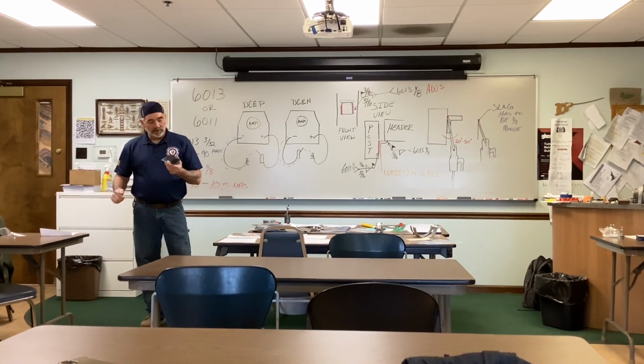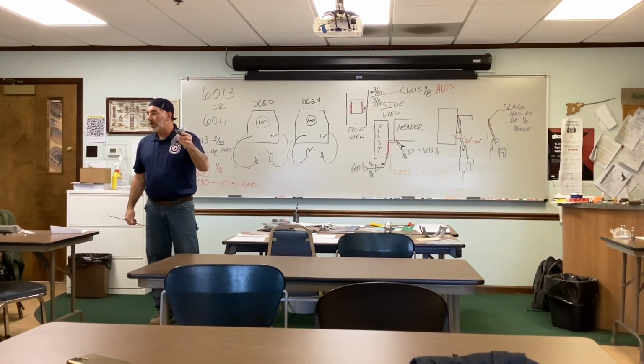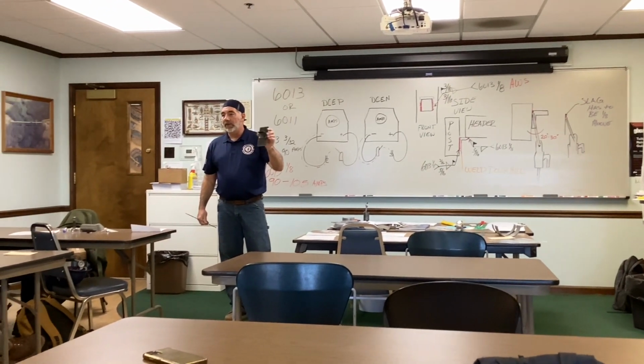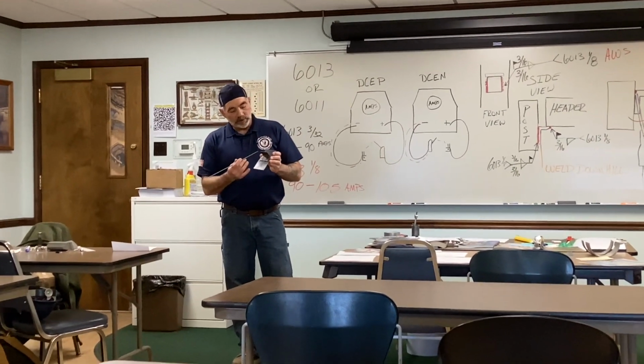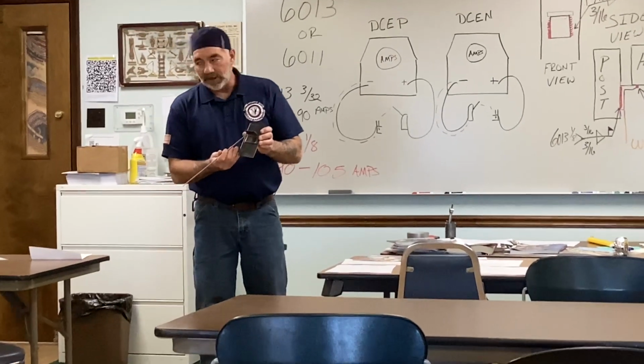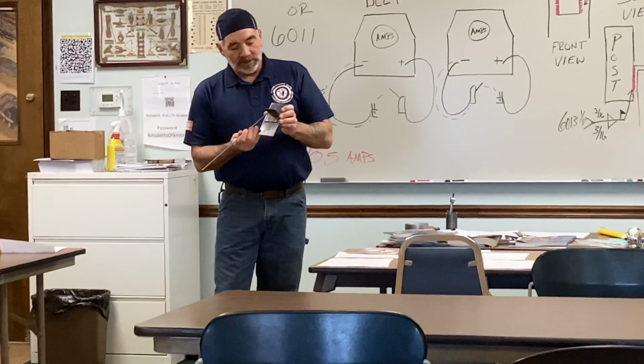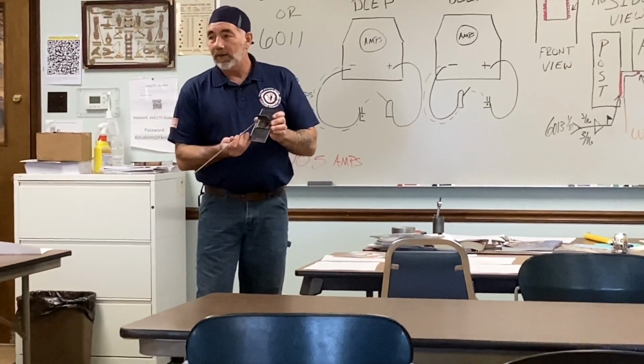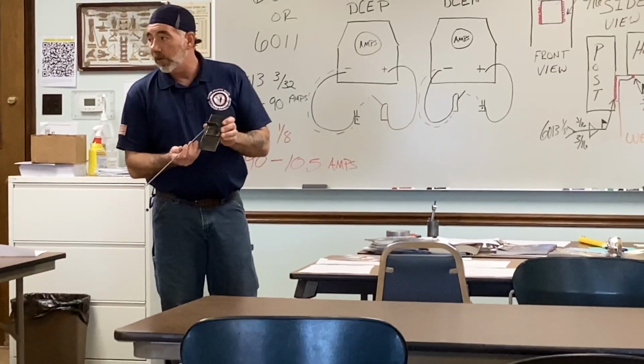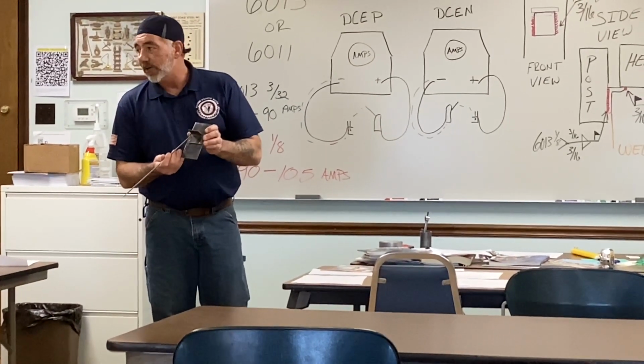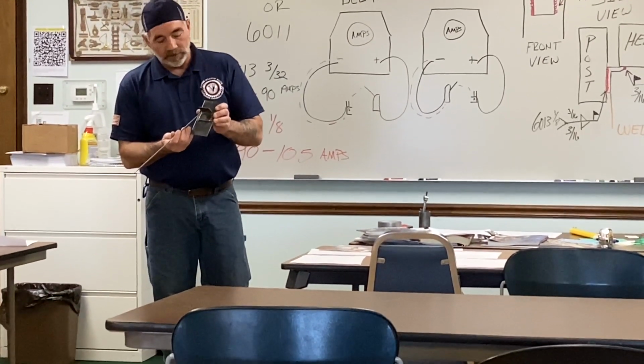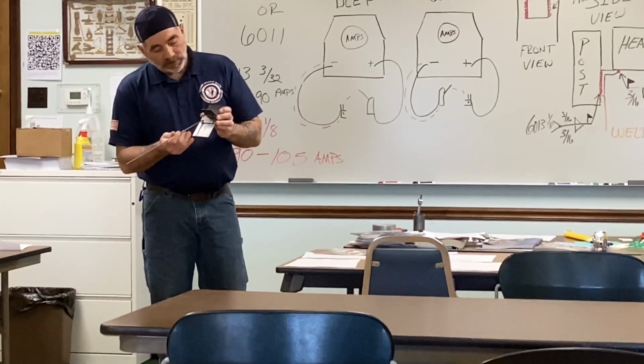So what I did here was weld up a little demonstration piece so you guys can see what a good weld and a bad weld looks like. On this side, when I welded it down, I kept it at about a 20 degree angle, a 16th off the steel as I welded down, and I wiggled left and right a little bit. And like I said, I concentrated most of my heat onto the angle. If you can see, I have a nice bead right here.